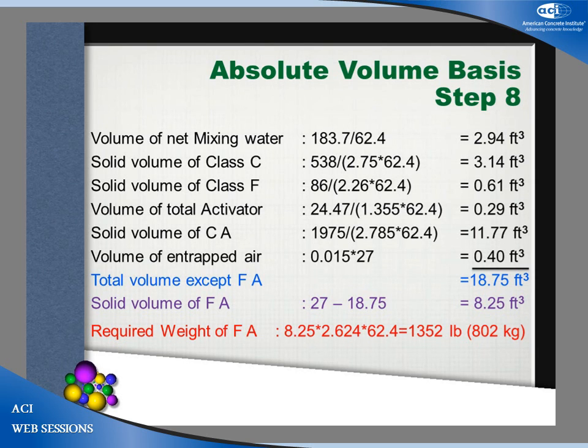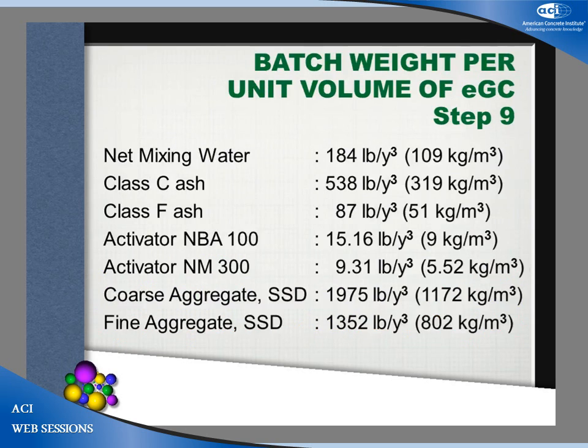So the solid volume of fine aggregate is 27 minus 18.75. So that will give 8.25 cubic feet as the volume of fine aggregate. So simply multiply with the specific gravity and 62.4, that gives the weight of the fine aggregate, 1352 pounds, that is 802 kg. So step number nine, simply the batch weights. We got everything: net mixing water, class C fly ash, class F, the liquid activators, NBA 100, NM 300, coarse aggregate and fine aggregate, everything we got.